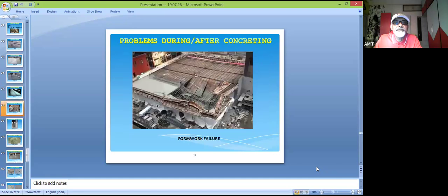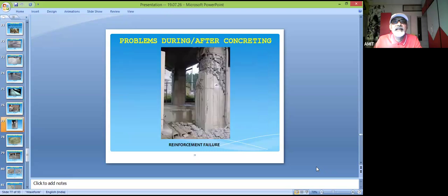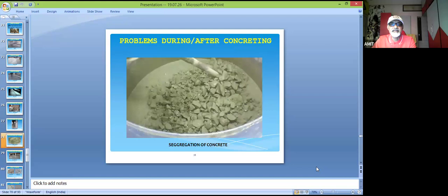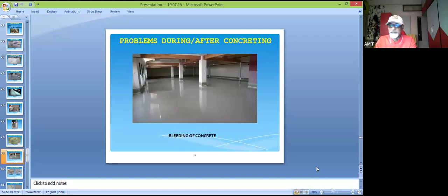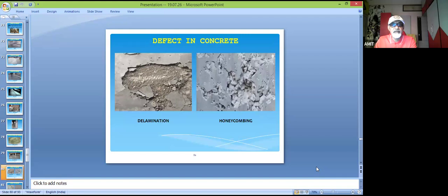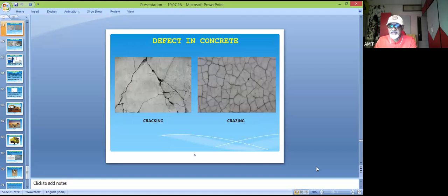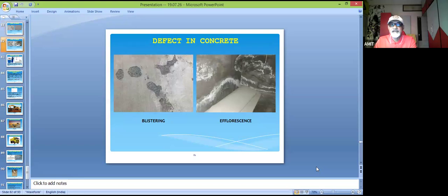Some failures are there. See, this is a formwork failure. It is a disaster. This is another reinforcement failure. Some common defects observed in concrete include segregation. This is the segregation of concrete. Then bleeding, delamination, honeycombing, cracking and crazing, blistering, and efflorescence. See, segregation occurs when coarse aggregates separate from cement mortar due to improper handling or excessive free fall.